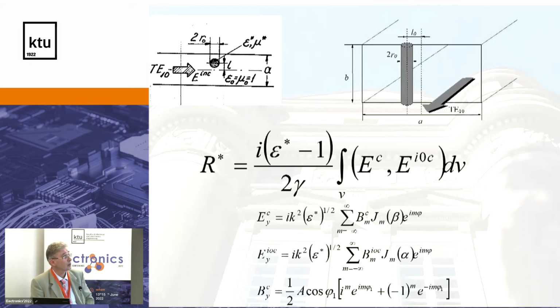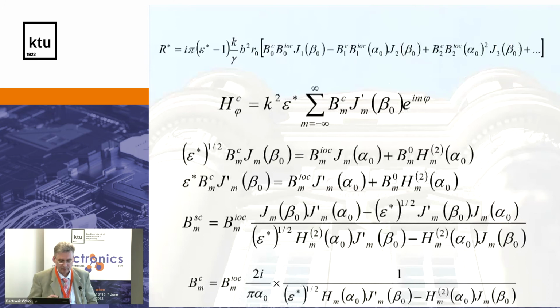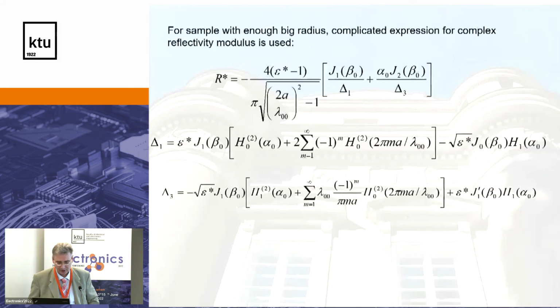So in our lab was developed the method of a needle-shaped sample placed in the waveguide, and from that to measure reflection and transmission. And again, because it's complicated stuff, I just show to know that mathematics is not so simple. Again, boundary conditions, Maxwell equations, cylindrical coordinate system due to the sample shape, and the reflection coefficient looks like that with all these coefficients, and from that you can extract the parameters.